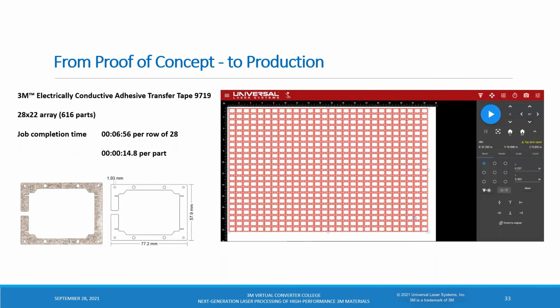So one of the obvious things here is, what about production? What we've done so far is showed videos of developing a beautiful sample, but we're all in the business of production. So you can easily go from concept or proof of concept to production on this system. By using the 9719 as an example, we created a 28 by 22 array of parts on the Ultra X6000 work surface. Each row of parts took 6 minutes and 56 seconds, or an average of 14.8 per part. There are performance tricks that you can use by sharing cut paths, et cetera, that we didn't go through, but you can effectively go from proof of concept and customer acceptance to production just by duplicating the design file within our software.